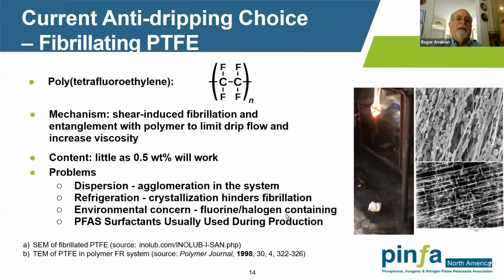So indeed, the current anti-dripping material, the drip suppressant of choice, is PTFE. Again, one of the trade names is Teflon from Chemours. But not all PTFEs work as a drip suppressant. So-called fibrillating PTFE has a crystalline polymorph such that when you expose it to shear, as you can see in the micrographs on the right, you form these microfibrils during extrusion and molding. And like the name implies, they are little filaments.